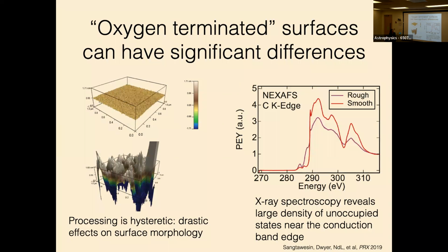And what we can see in the X-ray spectroscopy are drastic consequences to the electronic structure just from this difference in surface morphology. You can think of this as X-ray absorption that's probing the density of unoccupied states. This sharp peak here is the exciton peak in diamond. So everything to the right should be there. It's part of the band structure of diamond. Everything to the left should not be there and is basically just defect states. And you can see that this rough surface has this big tail of defects, whereas the smooth surface just has a couple of small peaks that are associated with the surface termination.